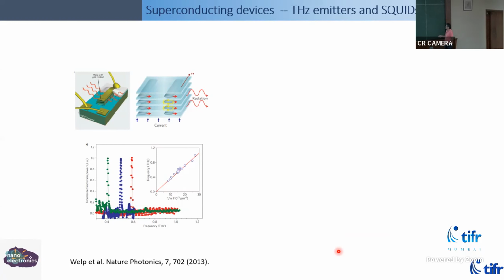Something that we are also interested in is continuous wave generation of terahertz radiation, and it arises very simply because I told you these copper oxide planes, that's where the superconductivity lives. They are 2D superconductors coupled by Josephson coupling between layers. So you have a network of 2D sheets coupled by Josephson junctions, and you can basically get radiation out of these Josephson junctions. I'll talk about Josephson junctions a little bit down the line, but the energy scales are such that the emission in this material is basically in the terahertz band, which has very few continuous wave sources that can deliver. So there's a fair bit of work.